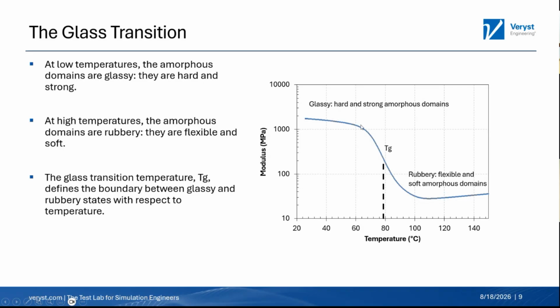The difference between melting and a glass transition is, if you're trying to impress your friends at parties, you call it a second order phase transition instead of a first order phase transition, which melting is. But it affects how we actually measure where this temperature is. And the other important thing about the glass transition temperature is that it tends to be a range of temperatures. You can see that the drop in modulus for this particular material starts dropping at about 60 degrees C and finishes dropping at about 100 degrees C. So that means that anywhere within this range, you have a pretty strong sensitivity to the temperature.